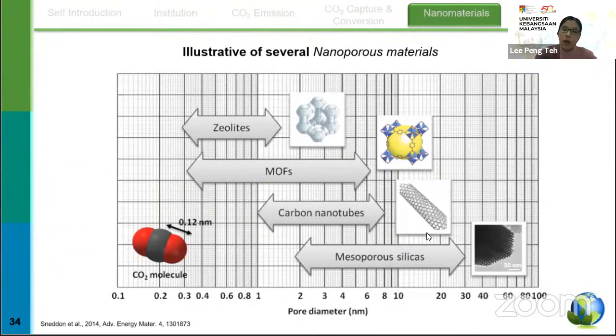Lastly, I would like to talk about mesoporous silica. If you know mesoporous silica, we have a few types. We have SBA-15, we have MCM-41. Compared to zeolites and also MOFs, mesoporous silica has a larger pore size, more than 2 nanometers. Zeolites are usually microporous in structure, so less than 2 nanometers. In the microporous category, it is less than 2 nanometers. If we say it is mesoporous, it will be 2 to 50. If macroporous, then it will be more than 50 nanometers.